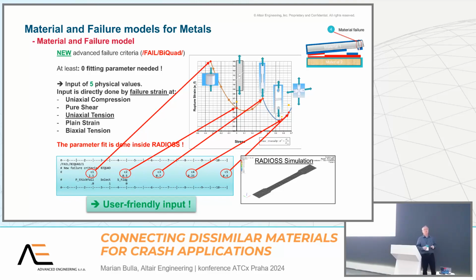surprisingly well. If you are not happy, you can fine-tune it by adjusting the entire curve. You can tune it with this parameter, which you obtain from the tensile test. And the entire curve will be shifted. And the shape of the curve is defined in the material flag, which is behind this flag. You can see it in the manual or ask me in the break so I can explain it to you even more. So this is for the failure criteria for base materials, like metals, whatever.